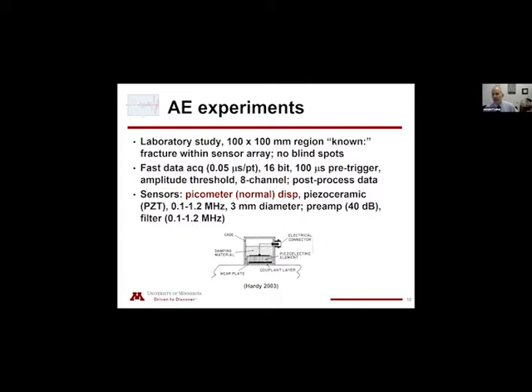And typically the data is processed after the test. We can look at counts in real time, but in terms of location or other types of processing, it's done later. The key feature of any type of monitoring is the transducer, the sensor. Because we're looking at very small amplitudes, the displacements measured by these transducers are on the order of 10 to the minus 12 meters. And the typical sensing element is a piezoceramic. One type of piezoceramic is PZT.